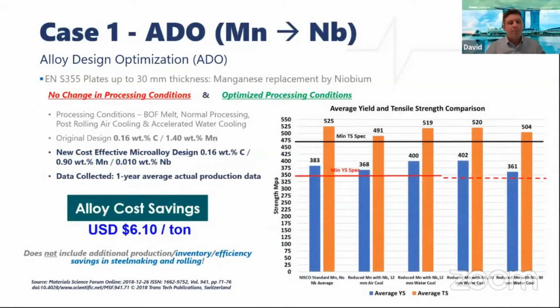Case number one is from published materials. As you can see, there's a source, and I'm very happy to share the publication with you. It was done in China to reduce the cost of EN355 plates, which were initially up to 30 millimeters thickness. And I will show you that we could even increase the range of that chemical composition up to 50 millimeters. It was a carbon manganese steel with 0.16 carbon and 1.4% manganese. And the manganese was reduced to 0.9 weight percent by the addition of only 100 ppm of niobium.